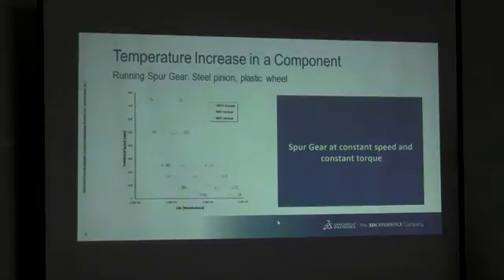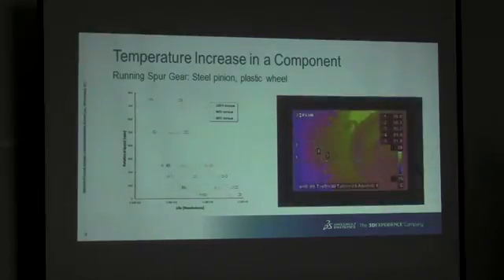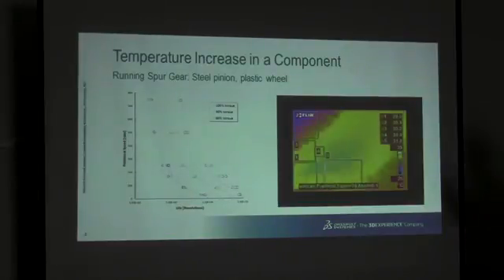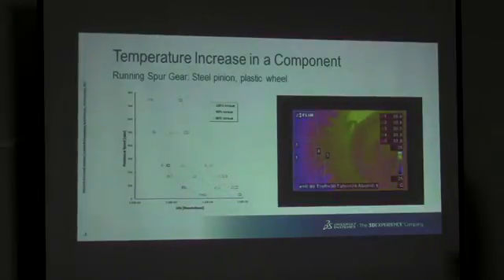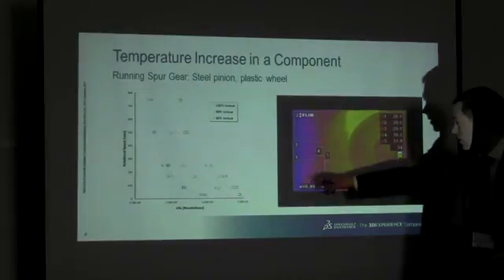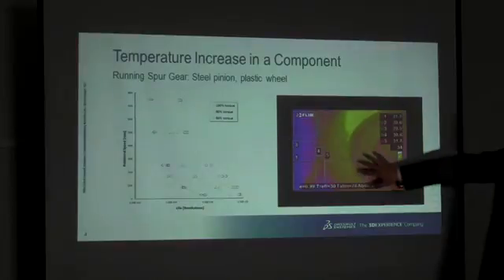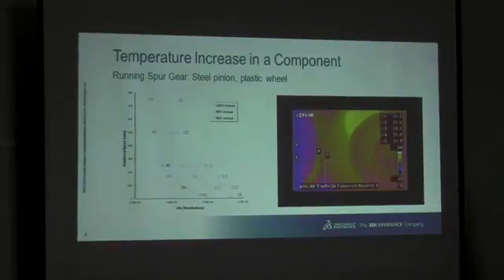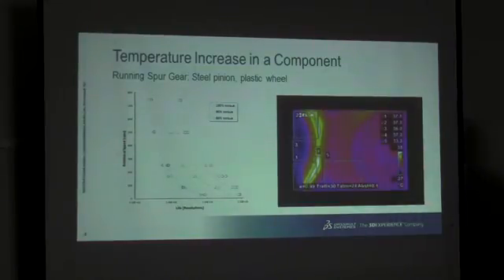So, this is what that looks like. We start out, and at the beginning, the plastic wheel is on the left-hand side. That's somebody doing a bit of hand waving in front of the screen. But we start the process and it slowly starts to run. So the plastic wheel is on this side. That is why you first of all see a bit of reflection from the steel. Then as it goes along, this is about 200 revolutions per minute, the temperature focus shifts entirely over to the teeth, which is logical. They see a lot of work.